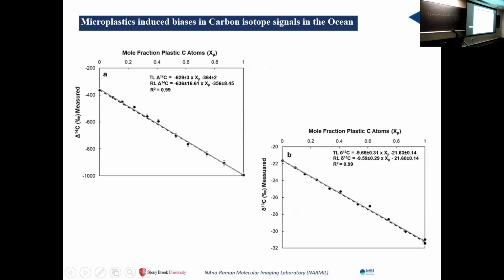That means this machine is measuring the isotopes from this microplastic, and we can see this here. The same thing with the delta 13 carbon, exactly the same. You see our experimental values, you see the theoretical line, and how they fit very well. So again, that tells us that the machine is measuring isotopic composition, and we don't know whether this isotopic composition came from the sediment or from the plastic. In an unknown sample, we know this here because we added the plastic there.